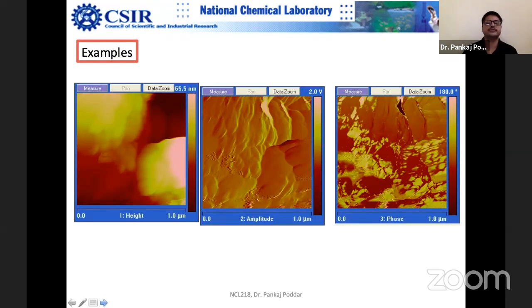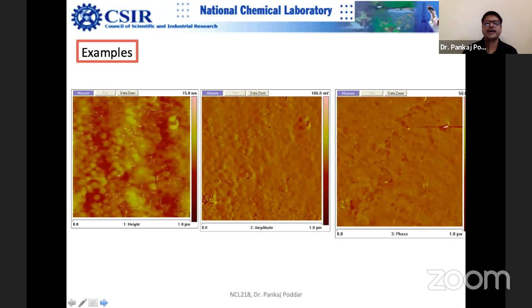This is another image where we have compared height, amplitude, and phase. These three pieces of information you get simultaneously, and you can compare them because the scan area is the same, 1 micron by 1 micron here, 1 micron by 1 micron here, 1 micron by 1 micron even here. You can see the scale is in distance, nanometer. Here the scale has to be in millivolt, but you can convert it into distance by a simple calculation. And this is the phase in degrees, so there is no need for any unit conversion here.